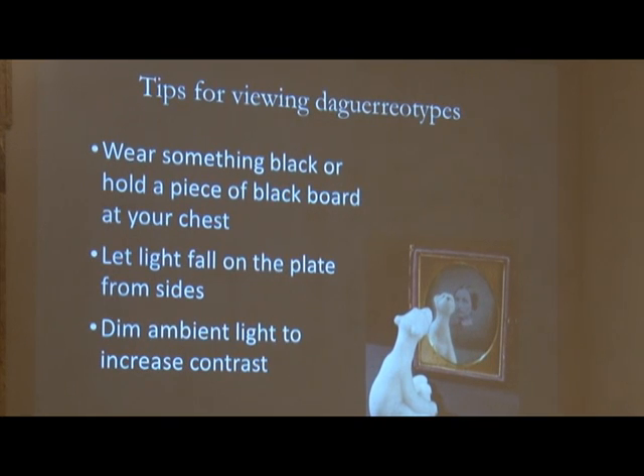When light comes in and hits the plate and hits the polish line perpendicular, if the light is perpendicular to the polish line, it catches light and it scatters light. And you know what happens when light scatters? It looks hazy. But that doesn't happen when the light direction is parallel to the polish line direction. And in the 19th century, the light source was often coming from the side, either from the window or candles. They didn't have overhead lights like we do now. So practitioners then worked with their environment and always finished the polishing in the horizontal direction. So remember to let the light in from the side.